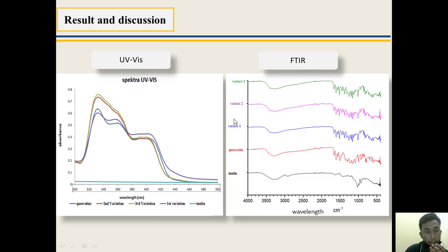The infrared spectrum of quercetin grafted inulin shows a new absorption band between 1608 and 1447, attributed to the C aromatic ring, which is a new absorption compared with inulin as the base compound. This suggests that quercetin has successfully grafted to inulin to form quercetin grafted inulin.